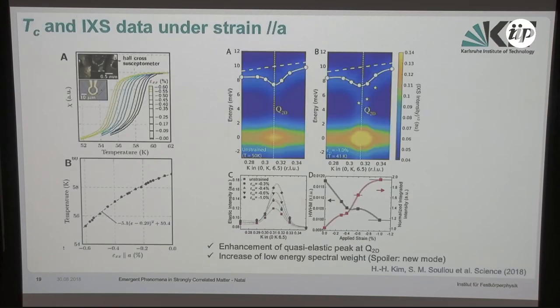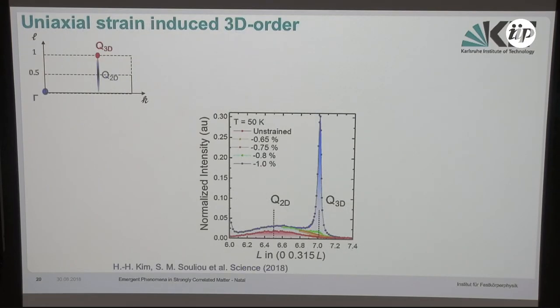Now we pushed as much as we could, and this peak was growing, but still we had no signature of long-range order. And then came the idea: well, maybe it's just like the magnetic field. So let's have a look at what happens at L equal 1, at the 3D wave vector. And this is now a scan along the L direction. The red curve is in the absence of strain, and you see this broad peak that corresponds to the 2D charge density wave.